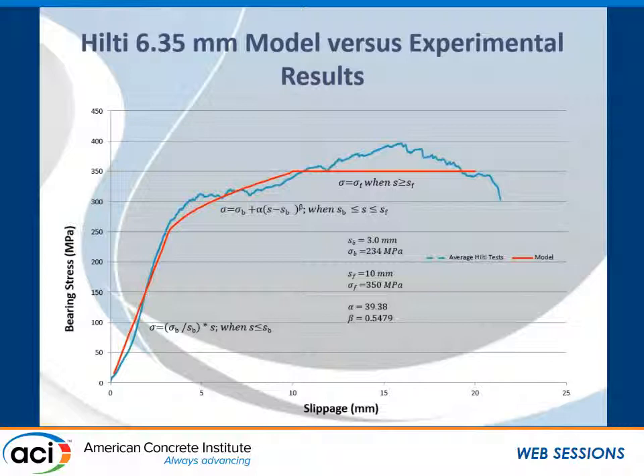The ultimate bearing stress was maintained while slip increased until failure occurred at ultimate slips of approximately 20 to 30 millimeters. Now note that the ultimate bearing strength and slips observed in connection tests with other types of anchor bolts, and to a lesser extent with the larger diameter KB3 bolts, was less than the 350 megapascals that we achieved with the 6.35 millimeter KB3s.